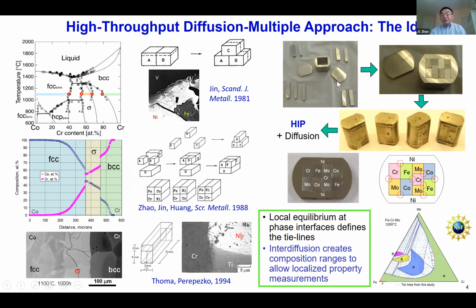So in this sample, this is a piece of nickel, an inch and a half diameter nickel. We cut a slice out from that, a chunk out of that, and then using wire EDM to hollow out the inside and basically polish it to make it clean. And then we put different pieces of metals like chromium and iron, nickel, and molybdenum inside. And then we put a cap on the top and the bottom. And then we send it out to a company to do electron beam welding, basically welding the cap inside. So that's in a vacuum state, inside the vacuum chamber. So the inside is vacuum, and then we use a hot isostatic press. So basically put this one in an argon environment and squeeze everything together at high temperature and pressure.